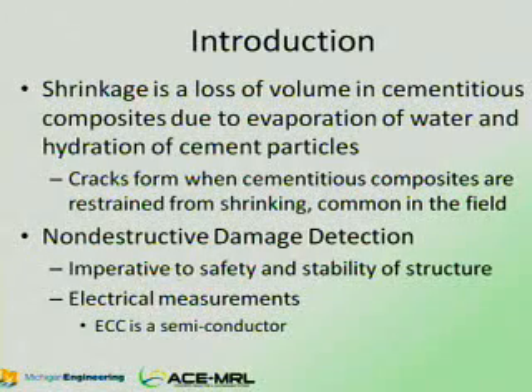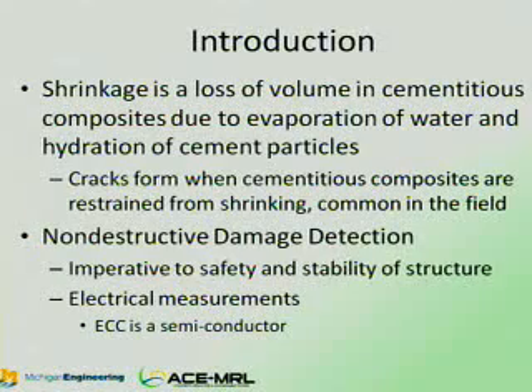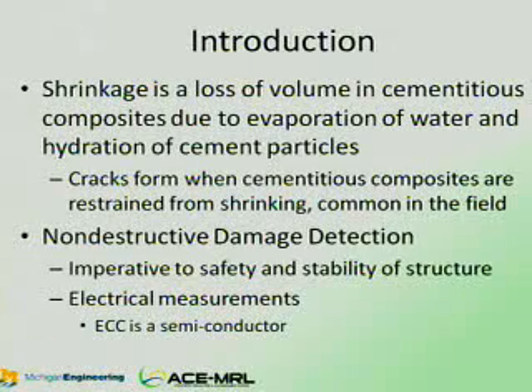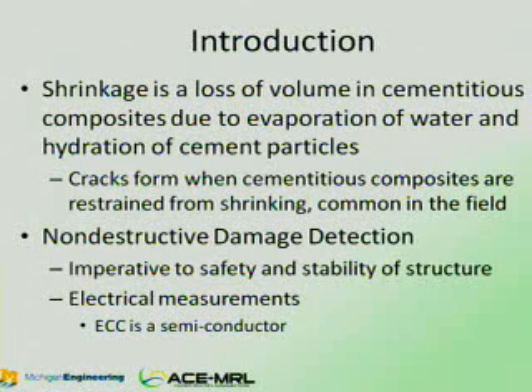Shrinkage is a loss of volume in cementitious composites due to evaporation of water and hydration of cement particles. Cracks may form when these cementitious composites are restrained from shrinking and not allowed to shrink freely. This is very common in the field.